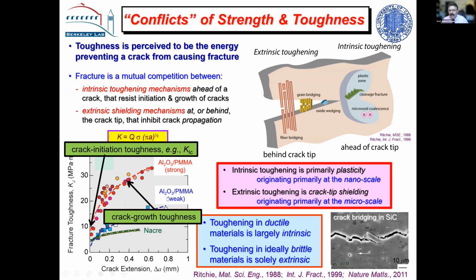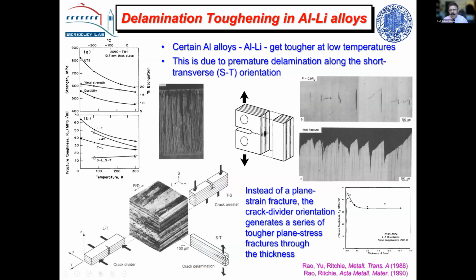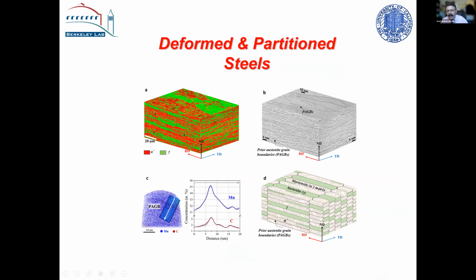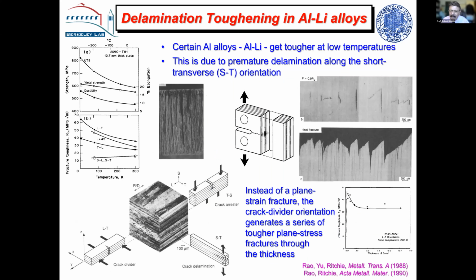Okay, so let's start with something a little bit old. I want to talk about steels, basically traditional alloys initially. And just to remind, before I get into this, there was a phenomenon that we looked at 20 years ago, 25 years ago, which we call delamination toughening, which has relevance to these steels now. These are aluminum lithium alloys. And prior to that, similar materials were the 2219 alloys, and they were used as the main tank of the space shuttle, which carried liquid oxygen, liquid hydrogen. And one of the characteristics of these alloys was they got tougher at lower temperatures.